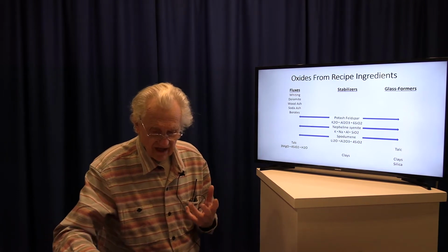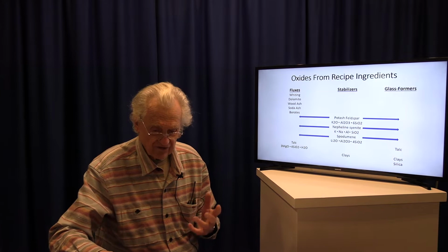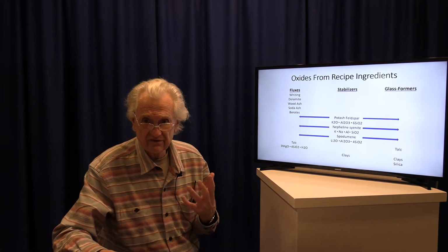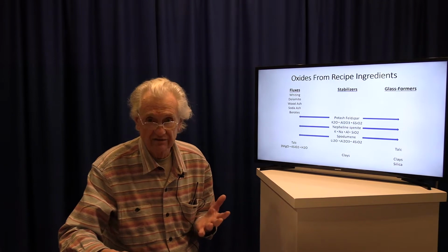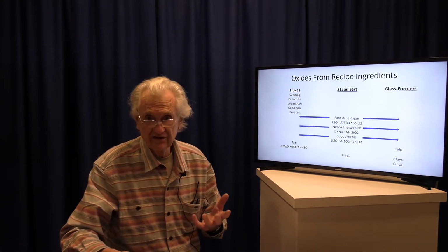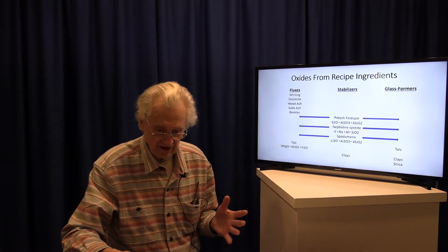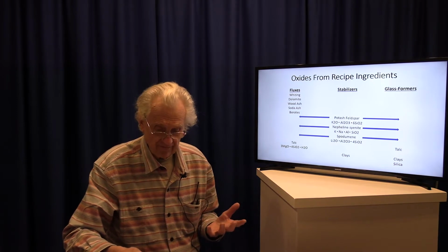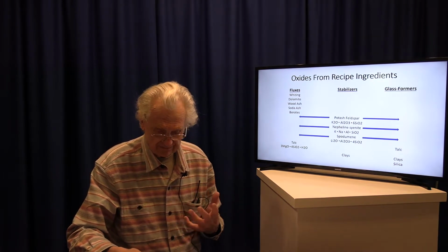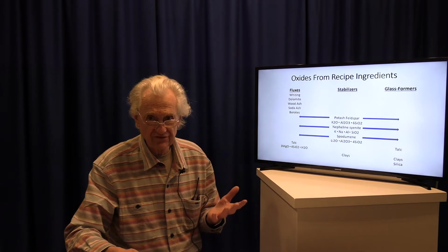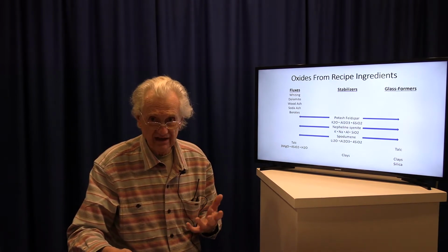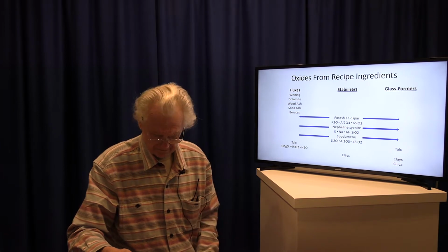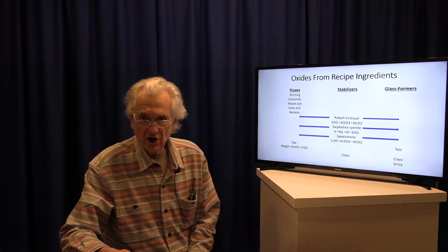So, for example, sodium carbonate, which is a source of sodium oxide, melts at a very low temperature. It melts in the range of cone 014 to 012, which is about 1,565 degrees Fahrenheit, very low. So the feldspar, which is another source of sodium, melts above cone 6. And Ferro Frit 3110, which is a fairly common frit, melts in the range of cone 07.